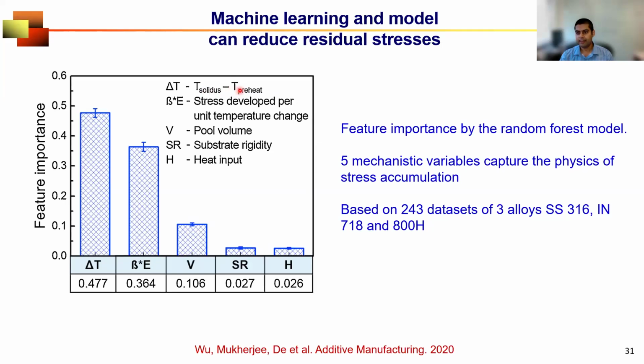variable controlling residual stress. If we go back to welding literature 40 or 50 years ago, we will see that in the welding industry, it's very common to preheat the welding plate before welding. What they are doing, they are increasing this T preheat to be able to minimize delta T, to minimize residual stress. So you see that using modeling results, then teaching machine learning algorithms using those modeling results, we are finding signs that have been there in the welding industry for a long time. That means these computational tools are enormously advantageous to be able to give you those insights that are already proven for a long time in various industries, but at the same time, discovering new science moving forward and helping us to be able to solve important problems in metal additive manufacturing.